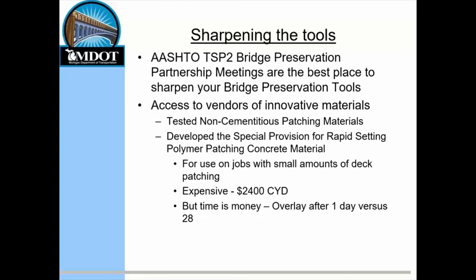And I say small amounts of deck patching because they are quite expensive. They run about $2,400 a cubic yard just for the material alone. But as you know, time is money. And these small deck patches using the non-cementitious patching materials can be overlaid after 1 day versus 28.